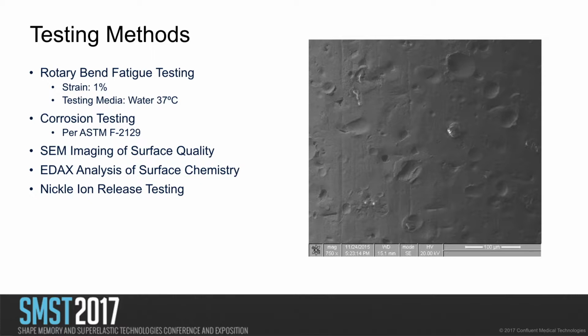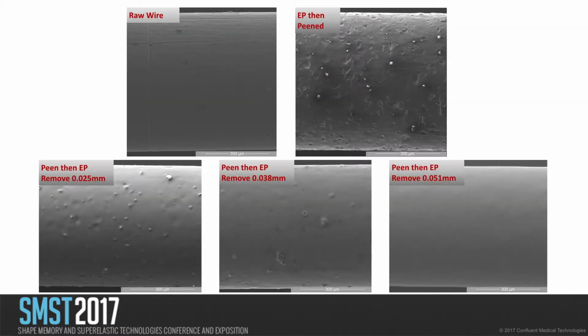The testing method that we used was a simple rotary bend fatigue test, run at 1% strain in water at 37 degrees C. We also performed corrosion testing per ASTM F2129, took SEM images to understand the surface quality of the parts, took EDAX analysis to understand surface chemistry, and did nickel ion release testing to understand biocompatibility. And this is the slide to focus on, because it contains most of the data we need to know.